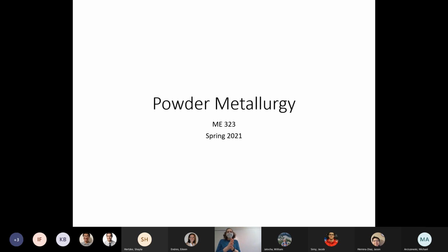Density. Conventional powder metallurgy parts that we get from sintering are going to have 5 to 25% porosity. If we're on the high side of the porosity, it's because we've intentionally made the porosity. But if we're producing parts where we don't want porosity, we're usually in the 5 to 8%. It's just there.